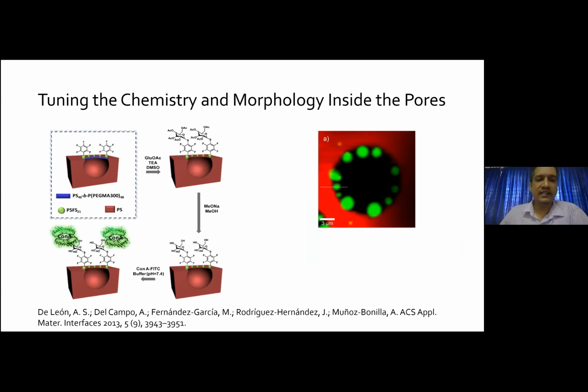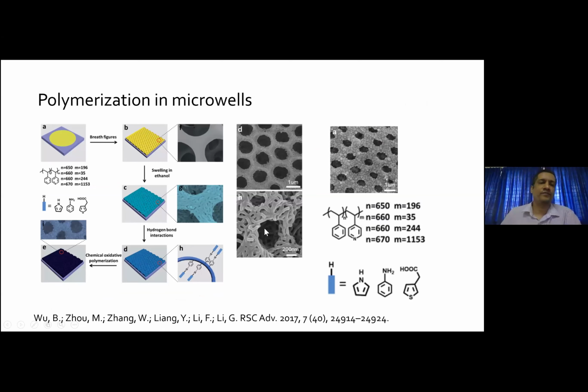And they tried to functionalize this perfluoro group present on the rim by click chemistry, which they did onto the surface after forming the breath figure. And this is fluorescent in nature, and they could also get a fluorescent image of this molecule on the surface.